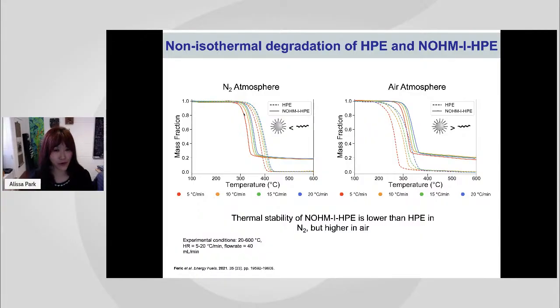So let's go back to the NOHMs material I told you about. The good thing is that these are non-evaporating liquids, so they will be very stable and stay as a liquid even if I leave them outside. If you look at the left-hand figure versus the right-hand figure, this is a nitrogen environment versus an air environment with high concentration oxygen. The dotted line is the polymer we started with, and the solid line is our NOHMs materials. Interestingly, under nitrogen condition, the polymer had a little better thermal stability. But as soon as we expose it to oxygen, the polymer starts to degrade very quickly compared to NOHMs. And as I told you, after 100 cycles, even in nitrogen condition, we had better long-term stability of NOHMs compared to untethered polymer. We were curious why.